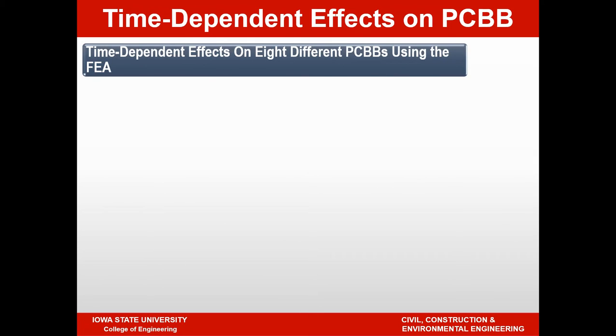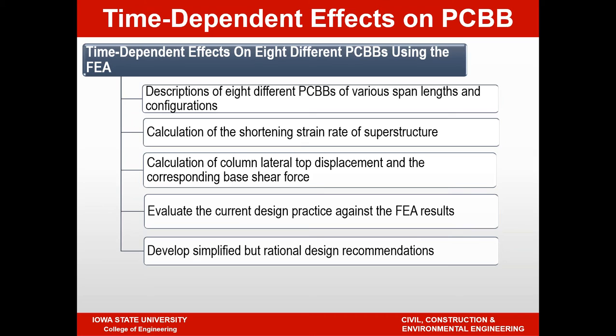If you go to the next slide, you can see the time-dependent effects on 8 different PCBBs. What we did in this case is that we understood how a frame in a bridge will perform, and we brought in 7 other bridges with varying span lengths and configurations. We calculated the shortening strain rate for each of the bridges like we have done for one bridge, and then we evaluated the column top displacement and the corresponding base shear, and we evaluated the current design practice against the finite element results. Then we developed a simplified approach to make sure that the current design procedure can be improved with a more rational, simple method. So let me share some of the bridges that we have looked at.